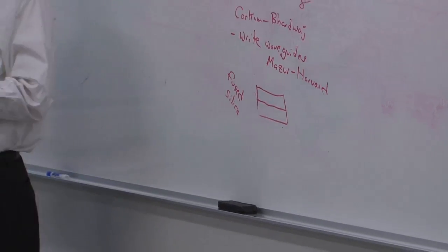Very, very controllable sort of laser damage occurs. Maybe you shouldn't even call it damage. The material becomes more compact. You heat it up, you almost melt it. It becomes a little bit densified. That raises the local refractive index. It becomes a waveguide. And it's really cute to show your visitors. You bring them to your lab. It's one of these Frankenstein things that you write a waveguide into glass right in front of them.